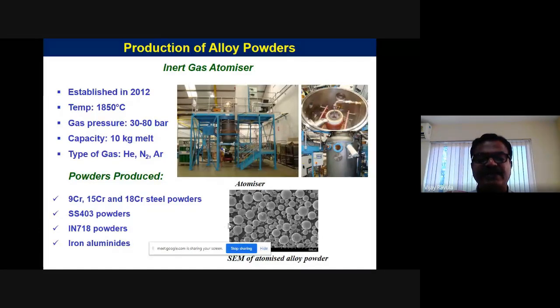So we made the different capacities: temperature is 1850 degrees centigrade, gas pressure we can vary from 30 to 80 bar, and 10 kg is the melt capacity, and we can use helium, nitrogen and argon gases for making these powders. And oxygen content is very, very critical in all these high-end applications. We made 9 chrome, 15 chrome, and 18 chrome steels, and SS403 stainless steel powders, IN718 and iron aluminides.